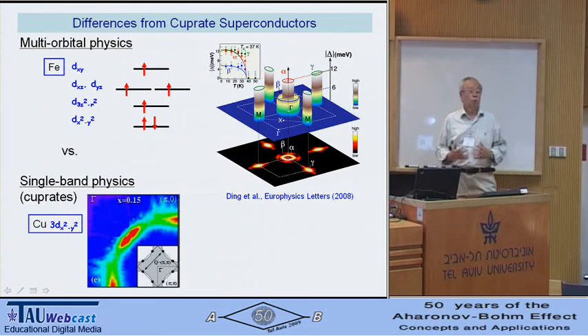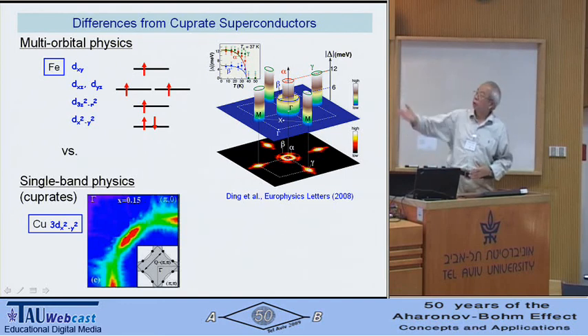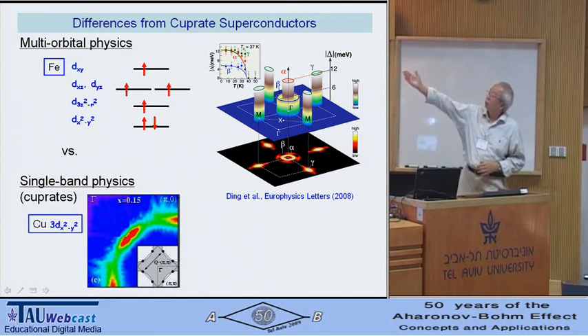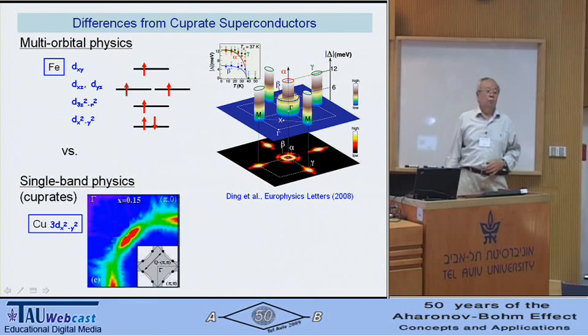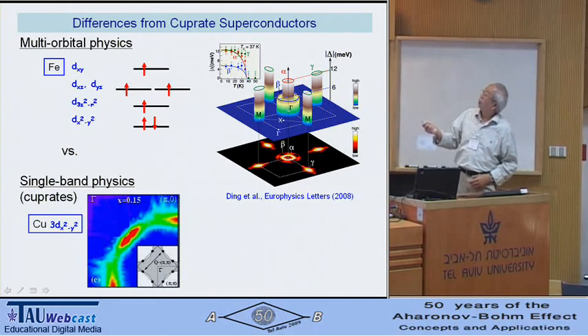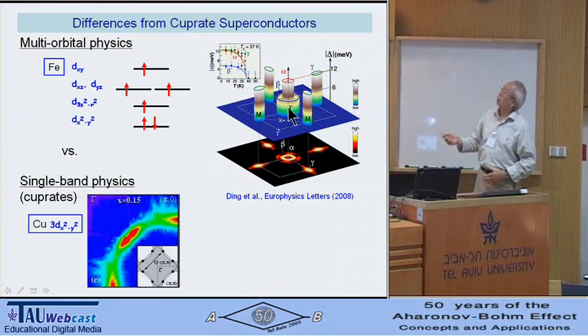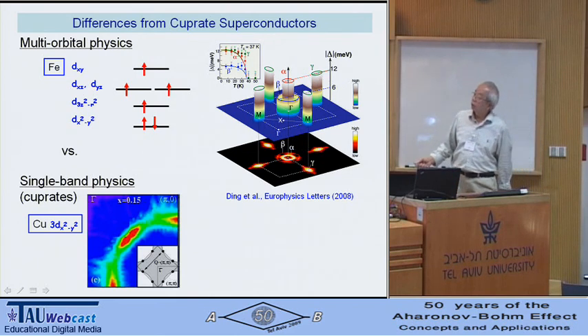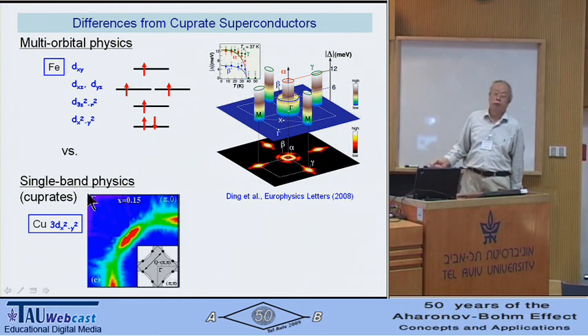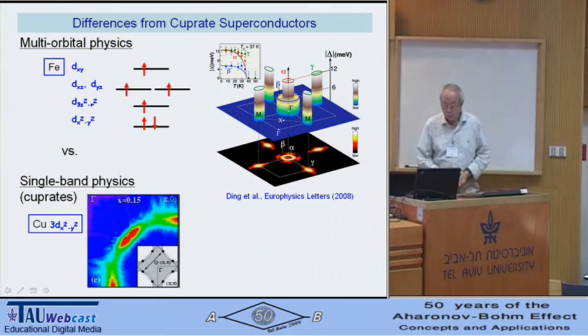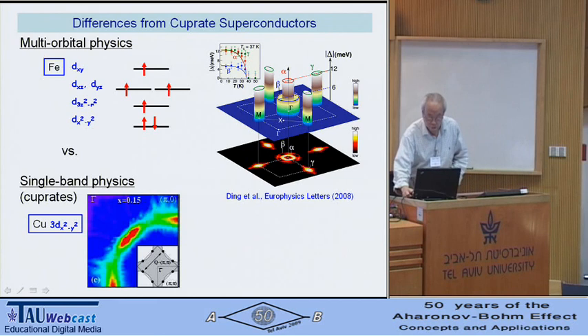Okay, what is the difference between the cuprates and iron pnictides? Basically, it's the band structure. In the iron pnictides, the band structure is derived from the iron d orbitals, as I indicated here. And sure enough, the photoemission result indicates you have multiple Fermi surface sheets. In the center, you have the hole pocket, and then outside you have the electron pockets. So totally 5 Fermi surface sheets. This is in contrast to the single-band physics involved in the cuprates, where you have only one single band. So that's quite different between those two systems.